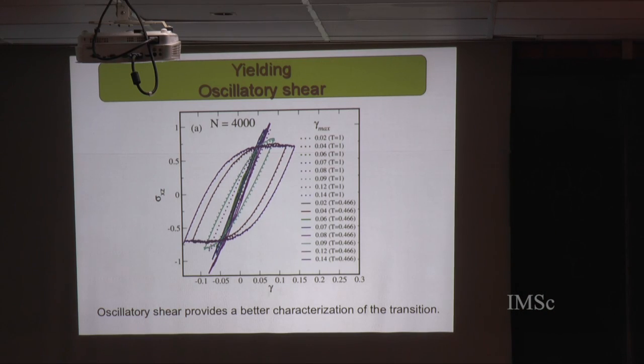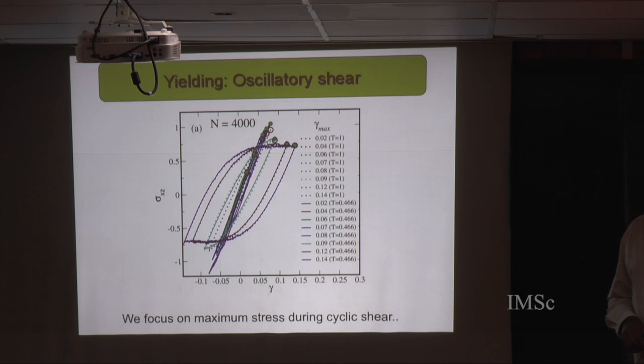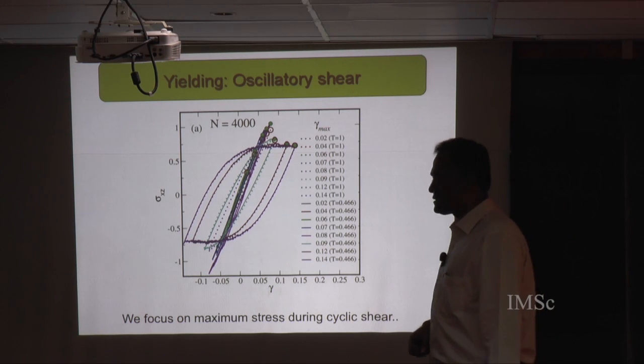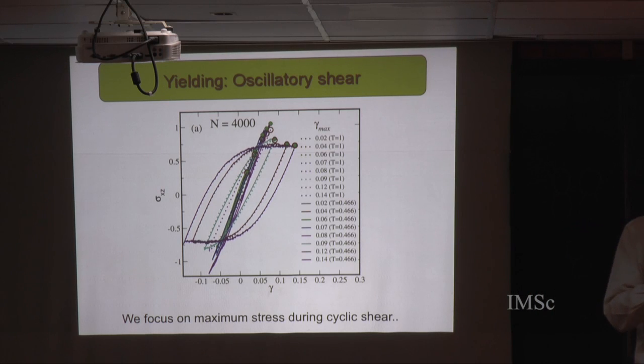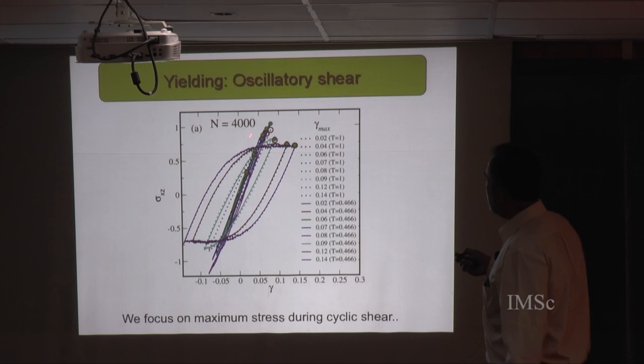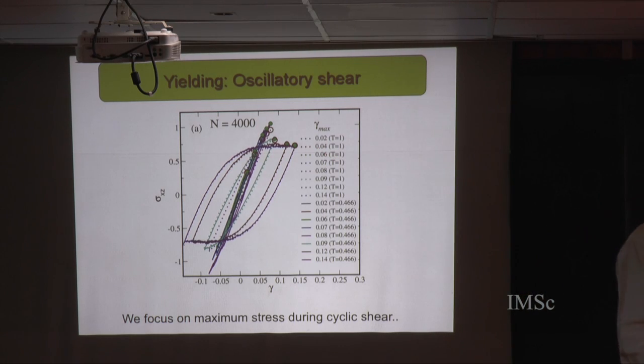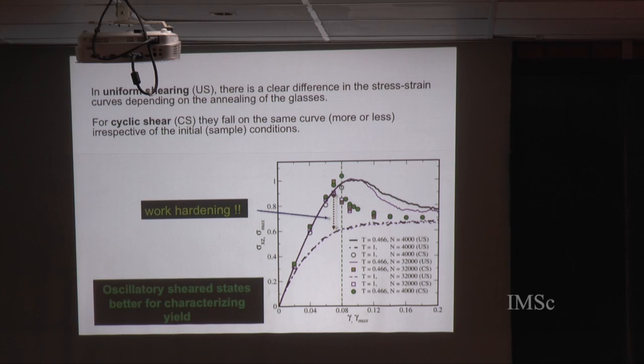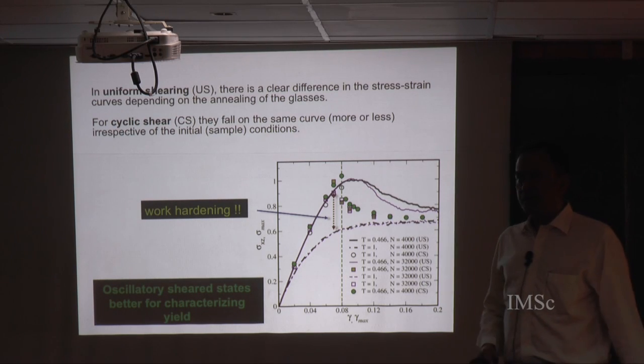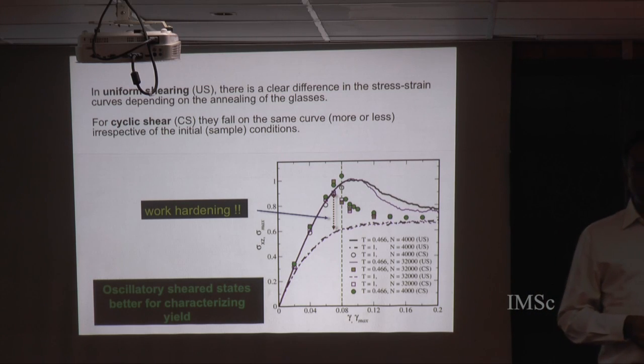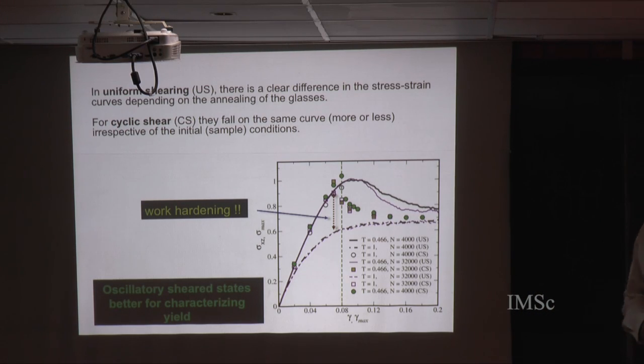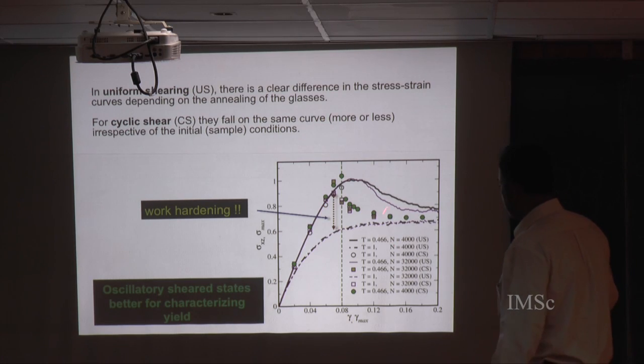I asked whether this helps identify where yielding is happening. One way to address that is, for each amplitude of deformation, to pick out the maximum stress generated in the system. When I do that, those are the dots, and you begin to see that there's a fairly sharply defined point where the behavior of maximum stress as a function of maximum strain changes. There are lots of different sets of data, but not all of it is necessary.